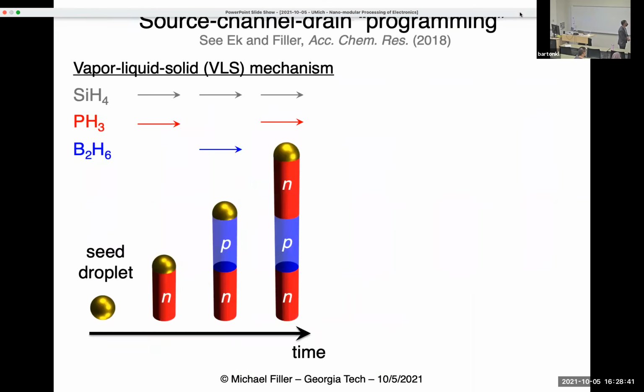Okay, so let's talk about wire growth. We use this technique called vapor liquid solid, VLS, to grow single crystalline nanowires from a metal seed particle. And the process is very simple. You deliver a semiconductor containing precursor like silane to this droplet. It reacts and deposits silicon. And when you've deposited enough silicon at a high enough temperature, this is a liquid droplet. If you keep adding silicon, then you will precipitate out a single crystal solid nanowire, just like sugar precipitating in water when you add enough sugar. This is the same thing. We add enough silicon to a liquid, and we spit out silicon solid.